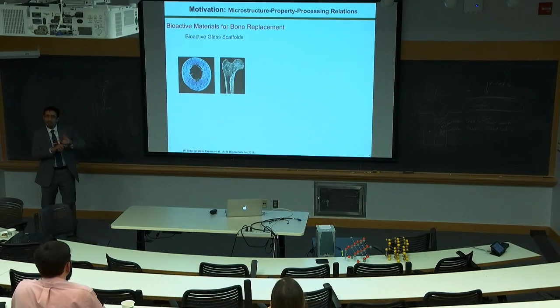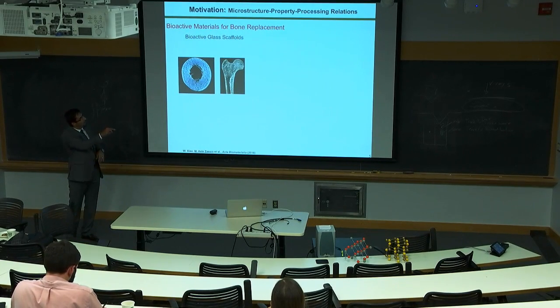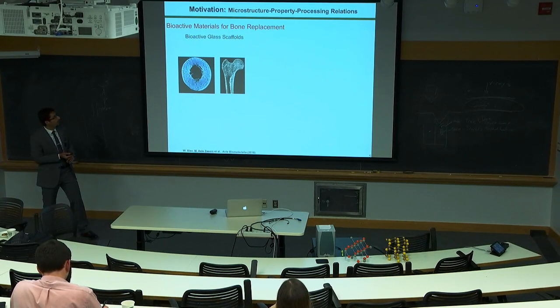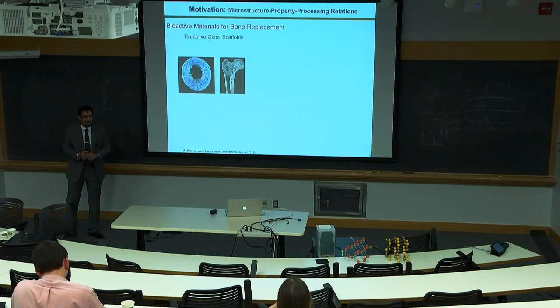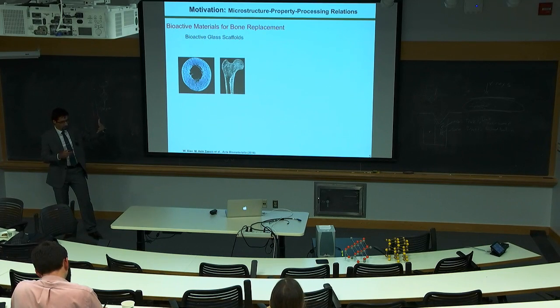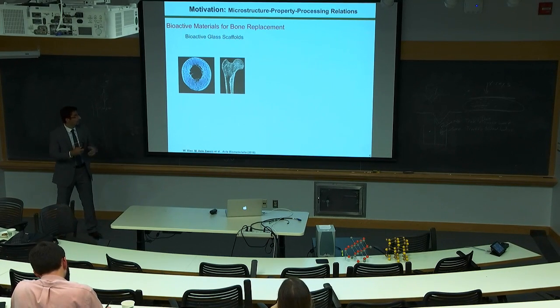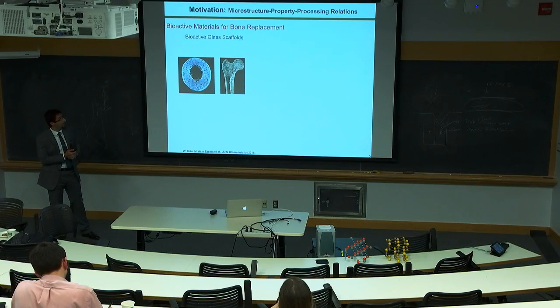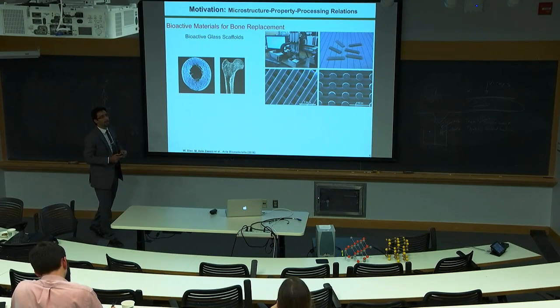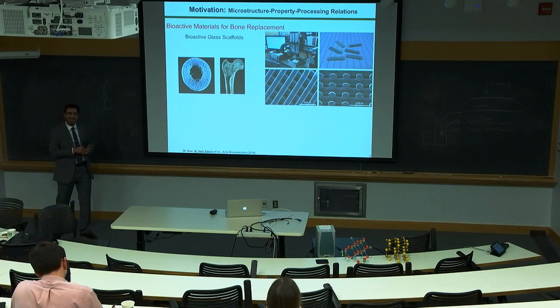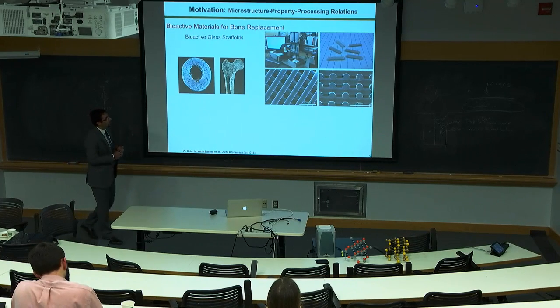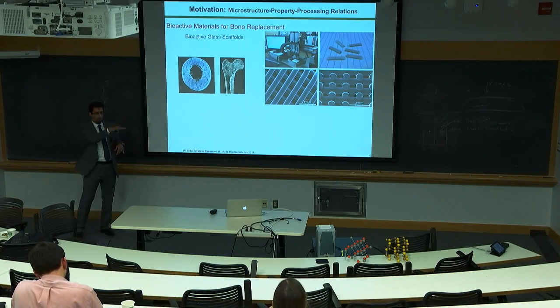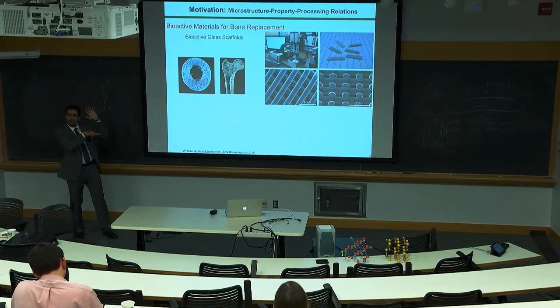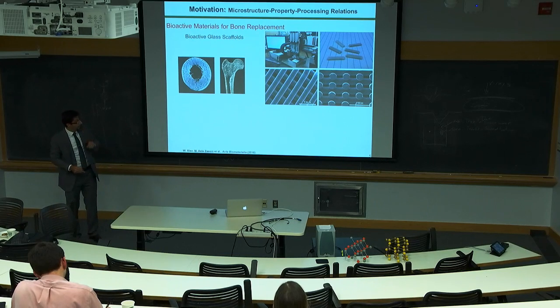Let's go to a completely different example. This is a bioactive material for bone replacement. This is the bioactive glass scaffold. We call it bioactive because the tissues can generate and go inside this bioactive glass scaffold. How do we make this? We make this through a kind of additive manufacturing called SLM, selective laser melting. Basically, we can have a scaffold with layers parallel to each other, and then another layer coming at 90 degrees.